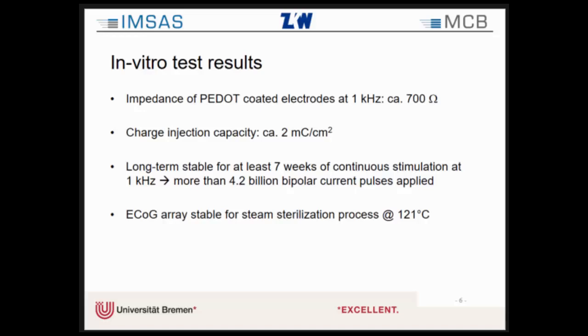We also evaluated the long-term stability of the array in Ringer solution for electrical stimulation. So for a visual cortical prosthesis, at the end we have to deliver many current pulses over a long time. And the question was, is this PEDOT-PSS coating stable for this long-term stimulation? And we showed that after a continuous current stimulation of 7 weeks at a frequency of 1 kilohertz, we couldn't observe any degradation of the coating, which gives us the result that the coating seems to be stable for electrical stimulation. We also proved that the electrode is stable for the steam sterilization process. Of course, for chronic implantation, we have to sterilize the array before implantation, and we couldn't observe any degradation due to the steam sterilization process at 121 degrees Celsius.